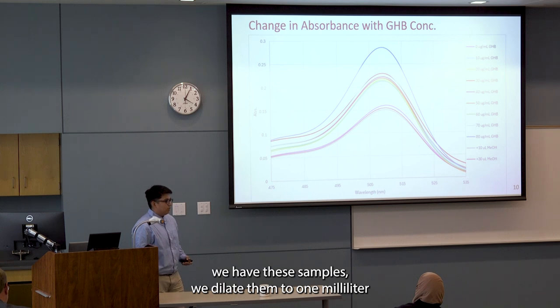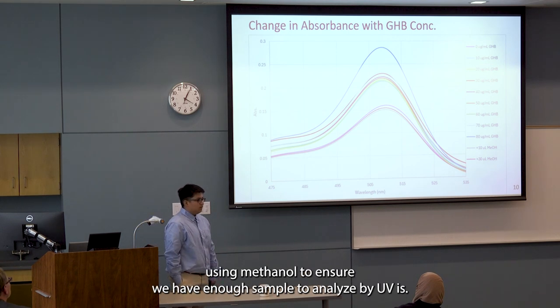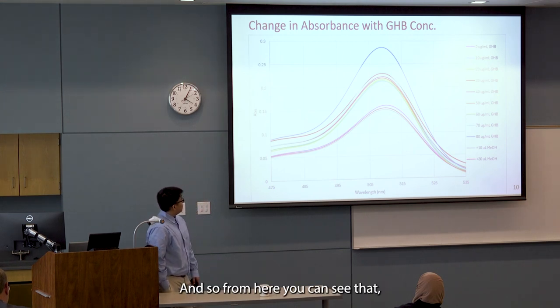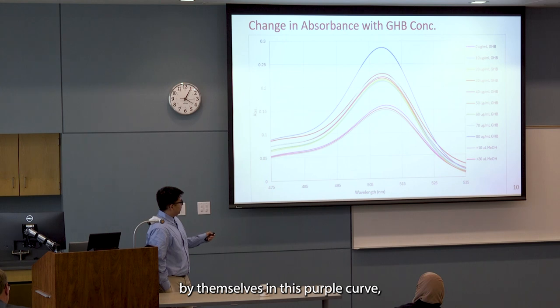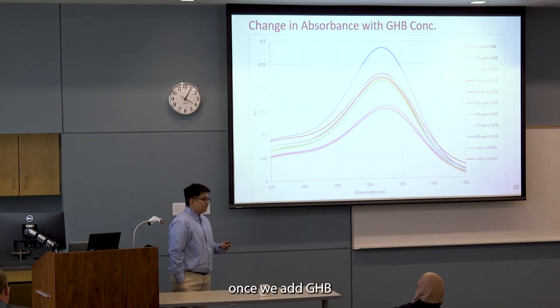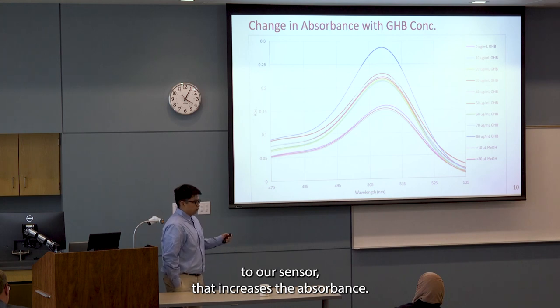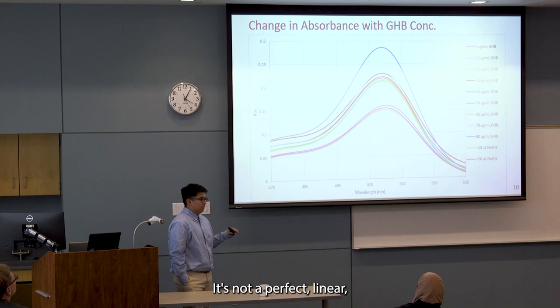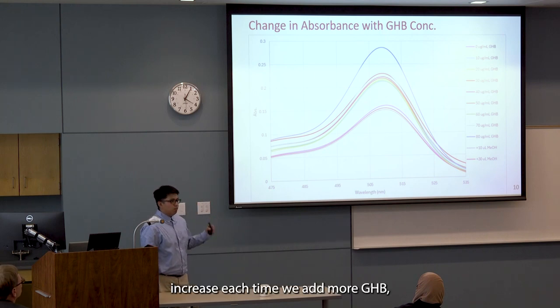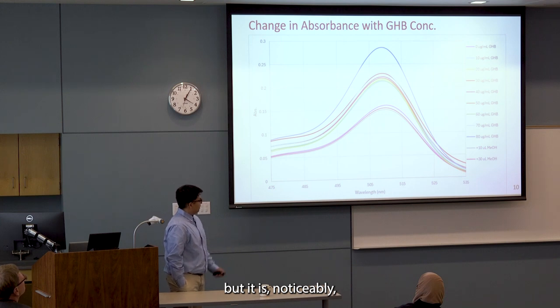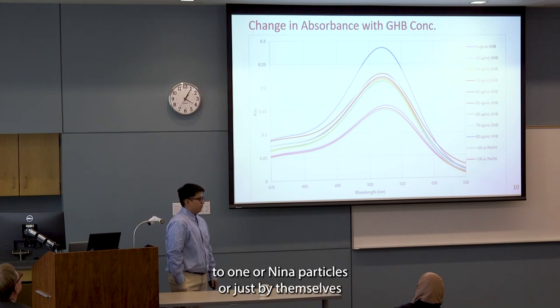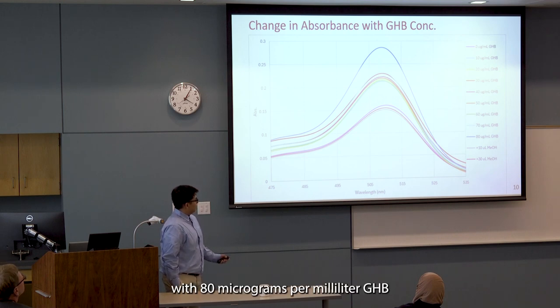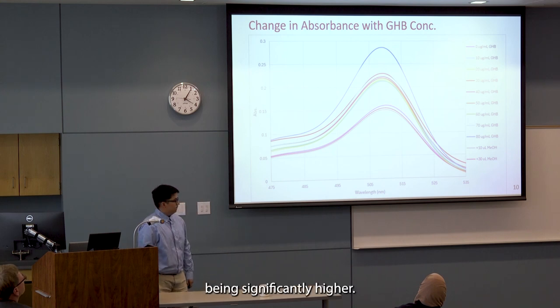And so once we have these samples, we dilute them to 1 milliliter using methanol to ensure we have enough sample to analyze by UV-Vis. And so from here you can see that when we just have our nanoparticles by themselves in this purple curve, once we add GHB to our sensor, it increases the absorbance. It's not a perfect linear increase each time we add more GHB, but it is noticeably increased compared to when our nanoparticles are just by themselves, with 80 micrograms per milliliter of GHB being significantly higher.